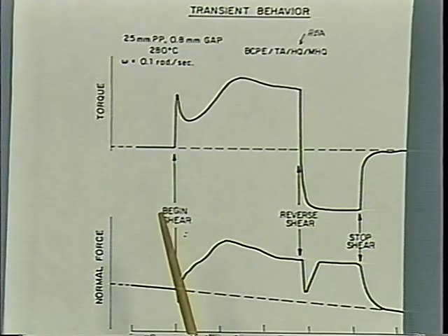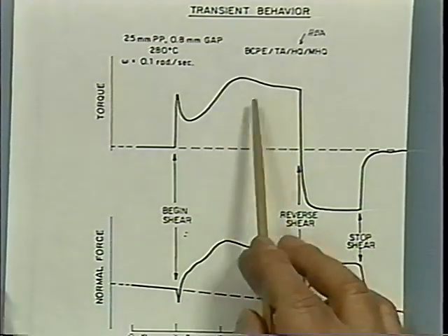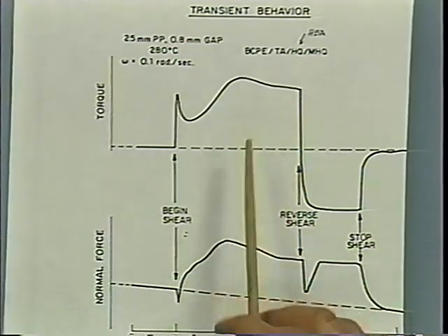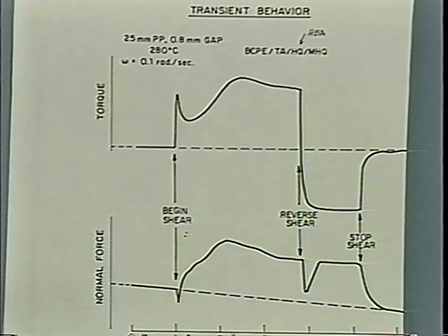in the order of 100 to 150 shear units. You need many, many shear units to reach a halfway steady condition in this experiment. For conventional polymers, a shear of 10 or 20 shear units would be sufficient to reach steady state.